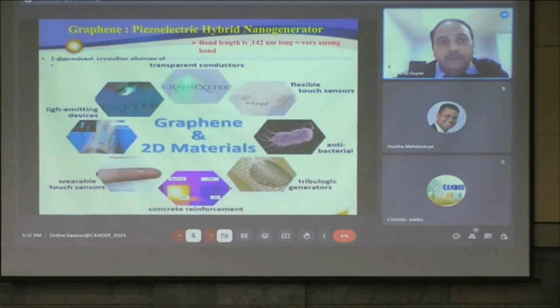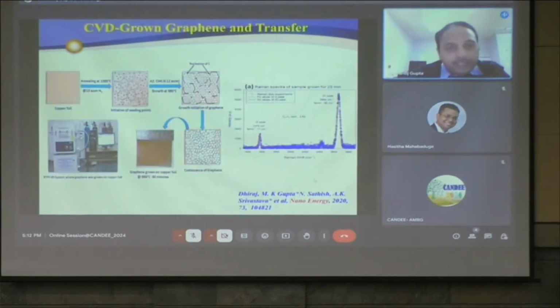And the growth of this graphene is also very interesting: we can achieve large-scale growth of graphene through the CVD technique. So we utilize the CVD technique to grow the graphene on copper foil. We control the gas and other temperature parameters to achieve monolayer graphene on the copper foil. Now, the next task was how to transfer this graphene from the copper foil to any substrate. Then only can we get the devices.